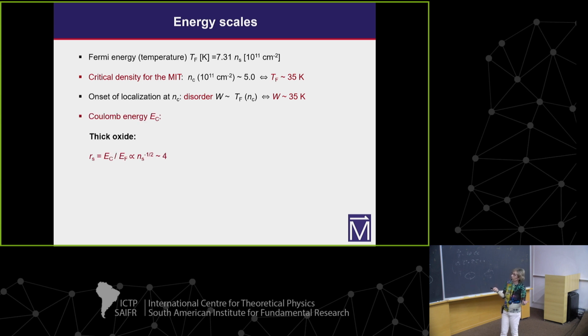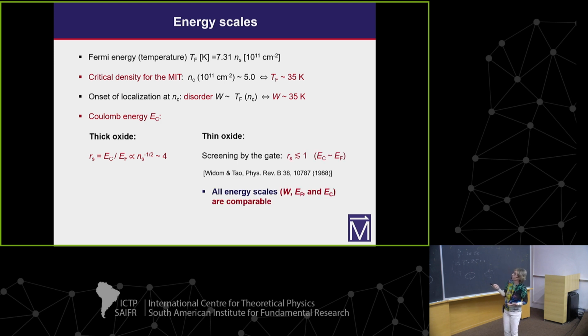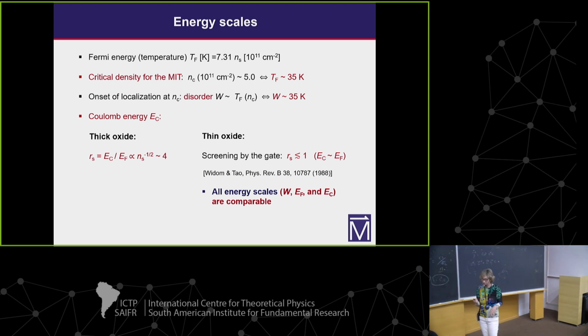In samples with thick oxide, where we have long-range Coulomb interaction, this is the dominant energy. But in the case of screening by the gate, this Coulomb energy is reduced, so all energy scales are comparable, similar to the case of these ultra-cold atoms where they found MBL.